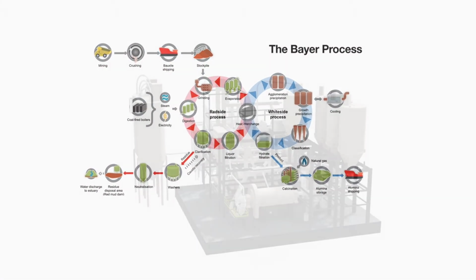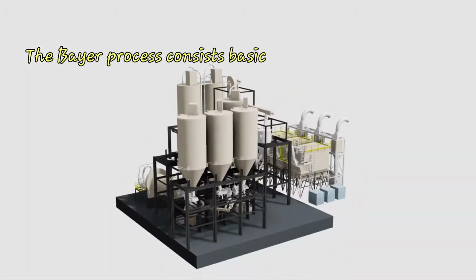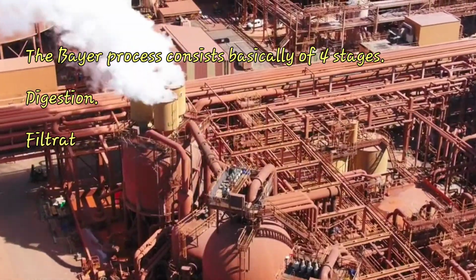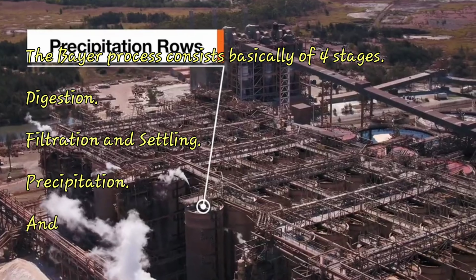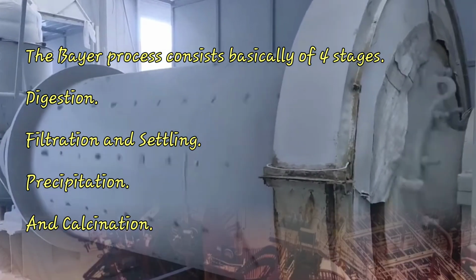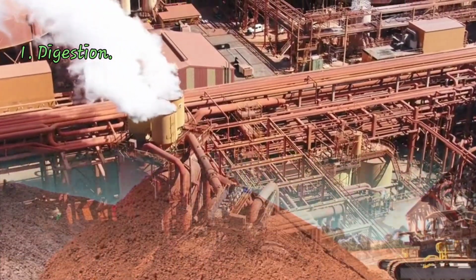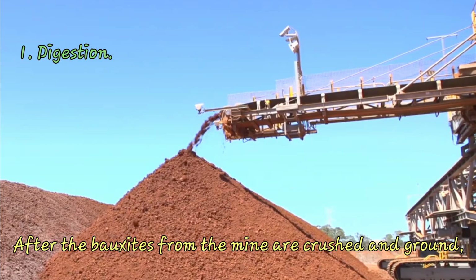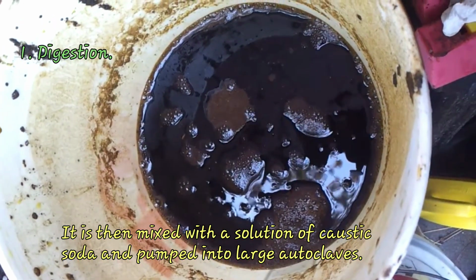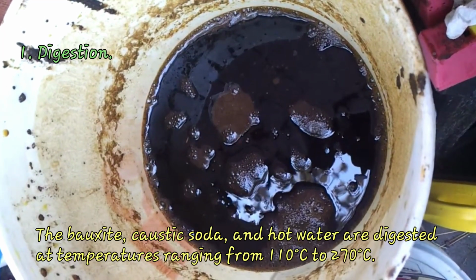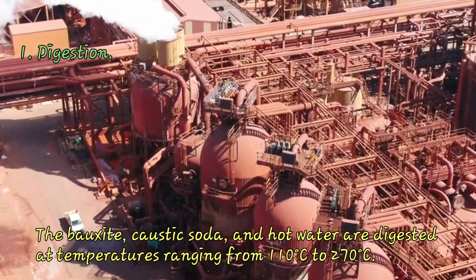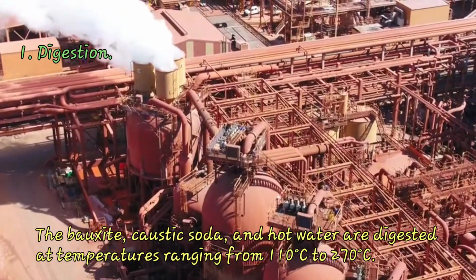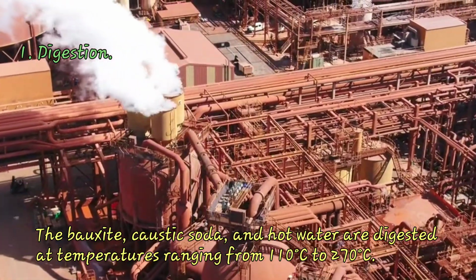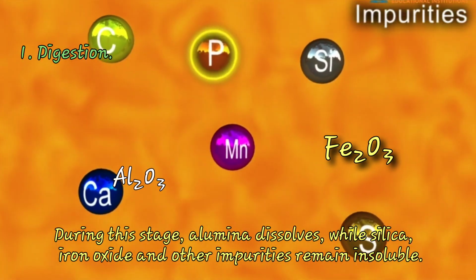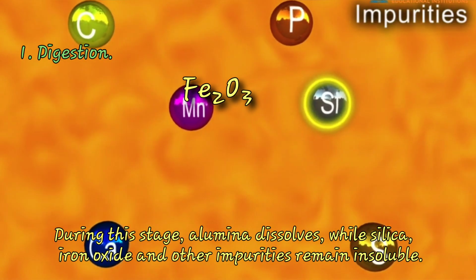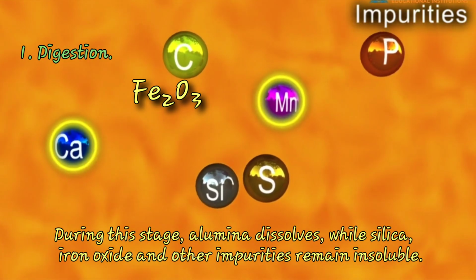The Bayer process. The Bayer process consists basically of four stages: digestion, filtration and settling, precipitation, and calcination. 1. Digestion. After the bauxite from the mine is crushed and ground, it is then mixed with a solution of caustic soda and pumped into large autoclaves. The bauxite, caustic soda, and hot water are digested at temperatures ranging from 110 degrees Celsius to 270 degrees Celsius. During this stage, alumina dissolves, while silica, iron oxide, and other impurities remain insoluble.